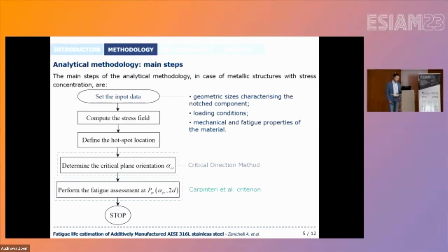That is, the crack nucleation location is defined. After that, the critical plane orientation is determined by employing a procedure which is based on the critical direction method. And finally, the fatigue assessment is performed by employing the Carpinteri criterion.